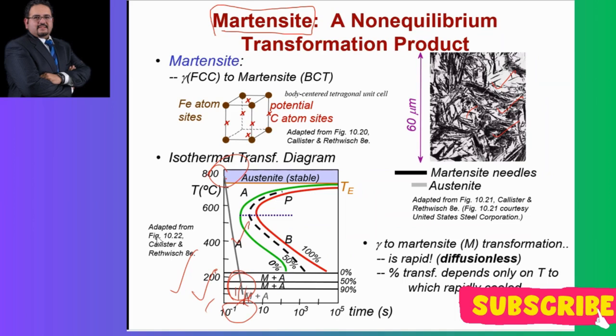Yes, students, do you have the time for diffusion? It is cooling from 727 to room temperature very quickly. Do you have enough time for diffusion in the case of martensite? No. In this case, you don't have time. So this is diffusionless, which means it's the other type of transformation, which is displacive.